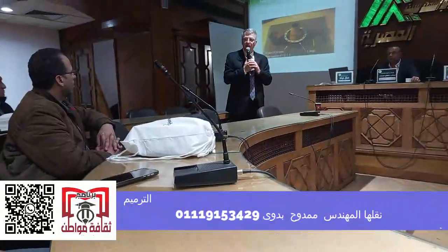Worked for one of the DOTs and found out that you can reduce 25% of the reinforcing bars for fracture if you put 0.5% fibers, because you have to offset the cost. They're not, like you said, free. We don't use them to reduce the steel, but if you reduce the steel, you make it easier for them to be cast. You use them to increase the toughness, strength.